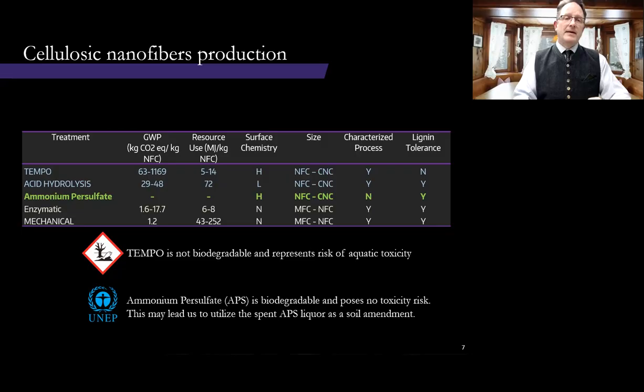Ammonium persulfate, the chemistry I'm targeting, suffers from very poor process documentation in the literature. And it also has some poor perceptions in the literature as far as reproducibility and reliability. But it has several advantages that TEMPO does not. First, it's been identified by the United Nations Environment Programme as a biodegradable chemical, and so therefore non-toxic. And it has the added capability of being able to tolerate lignin-containing biomass. So the implication for our process is that we potentially have an opportunity for our spent ammonium persulfate liquor, after we've finished with our oxidation, that perhaps we can return some of the sulfur and nitrogen that are left over back as a soil amendment.